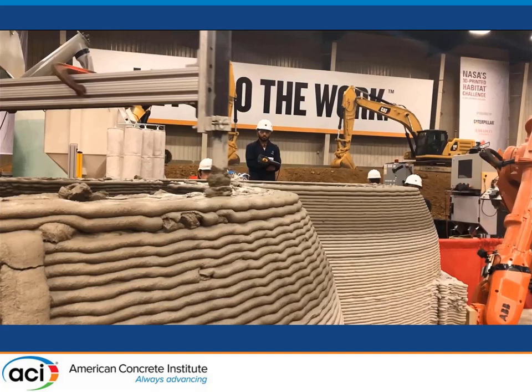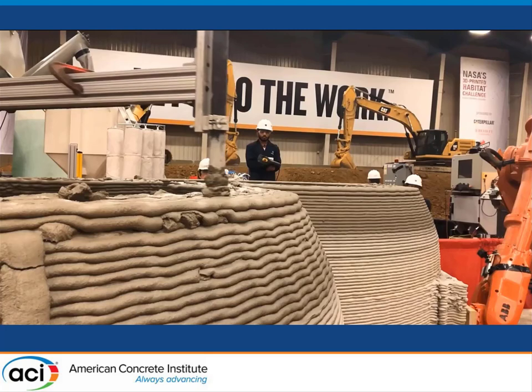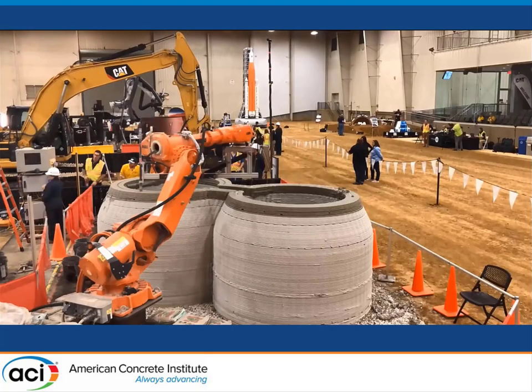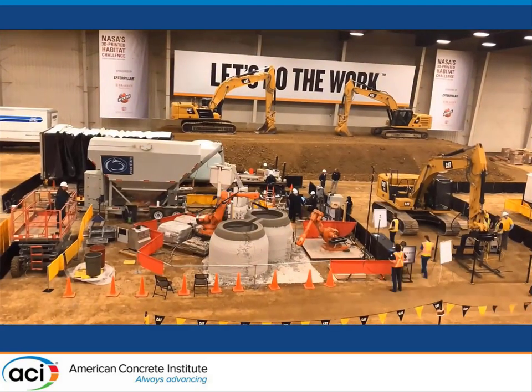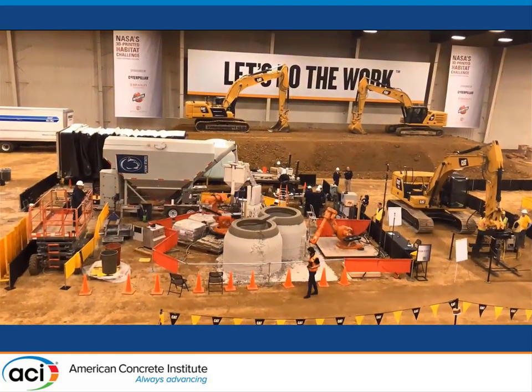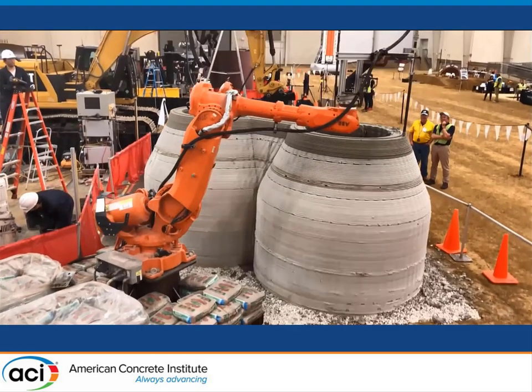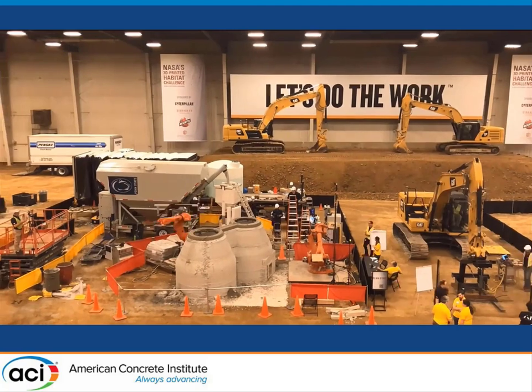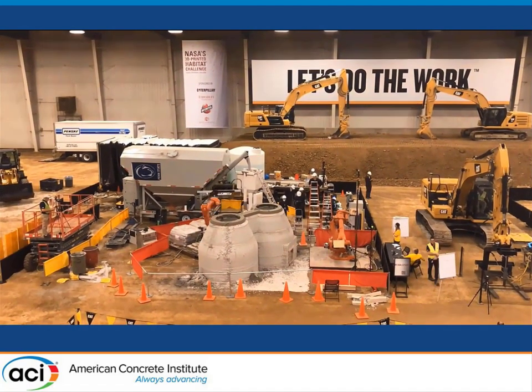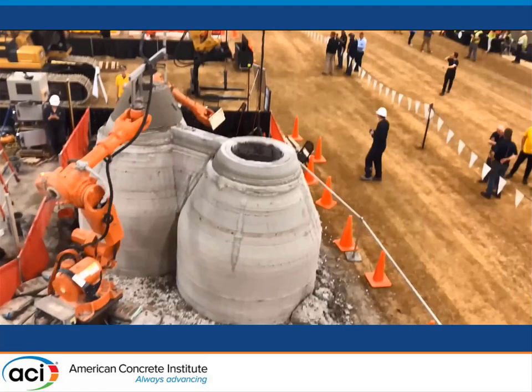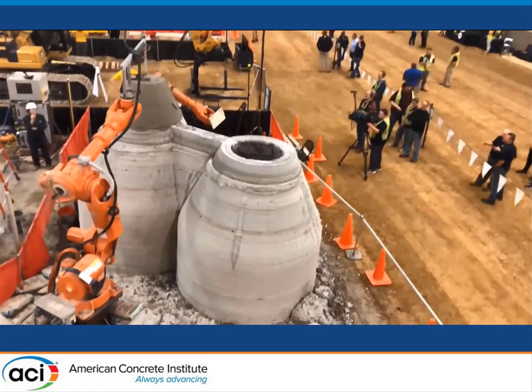We have some questions regarding cracking due to cold joints and delamination due to lateral loads. Could you comment a little bit on that? Sure. One of the big problems in digital construction is related to the cold joint. For this construction, as you can see here, we did everything over 3 days, so we had some level of cold joint. And when the construction was done, NASA did some tests. They crushed the 3D printed habitat, and we saw that most of the failure happened in the cold joint.